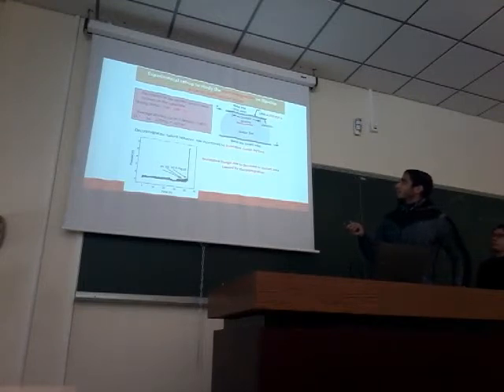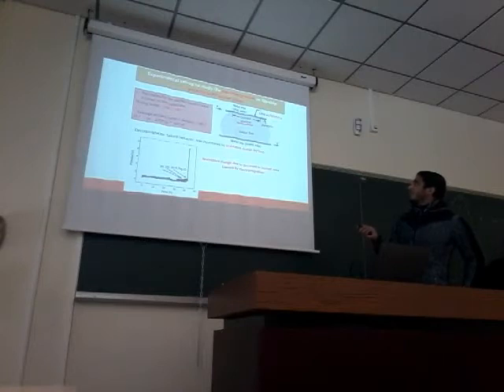As we can see here, we used electrodes for the applied current from copper lines on the substrate. The experiment was operated at temperatures from 100 to 140 degrees Celsius. Average applied current density, as we can see here, is in this range. And the contact window diameter is 100 micrometers. Electromigration failure was monitored by studying resistance change over time, using 24 samples.